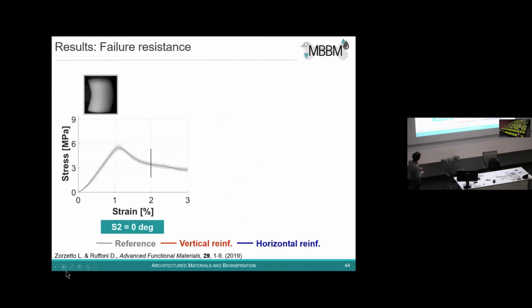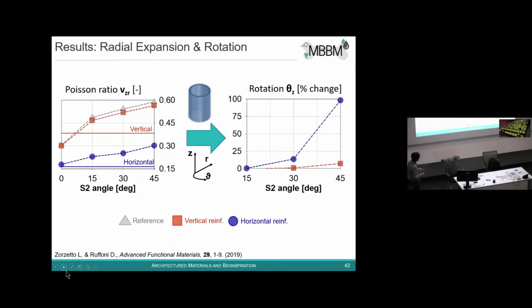What we also did, I wanted to show maybe this plot here. We ran some finite element simulation of the same structure to understand a little bit how the structure is deforming. And what we saw is that if we introduce, for example, the horizontal fibers, what we are blocking is the expansion of those cylinders. So when we compress and we measure the Poisson ratio, so the expansion perpendicular to the direction of compression, we saw that with vertical fibers, we have pretty much similar behavior as with no fibers, and with horizontal fibers, we are blocking the expansion. We have a much smaller Poisson ratio.